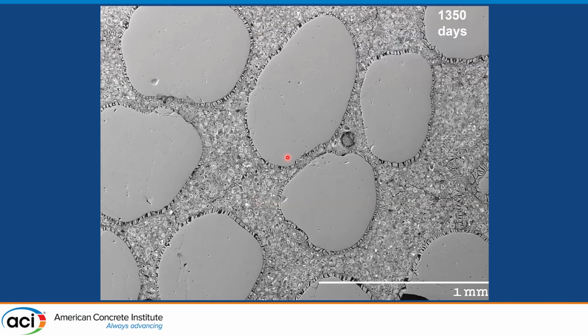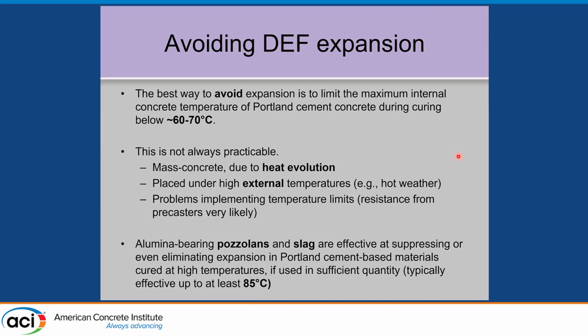And over time, of course, with more time, you see every one of these sand grains. These are Ottawa sand mortar bars. You see the gaps surrounding each one of those aggregates due to the swelling, plus some cracking in the matrix. And that's what's causing the swelling. The gaps formed due to the swelling of the paste. The ettringite in the interfacial transition zones is just a sign. It didn't cause the expansion, it just is there.